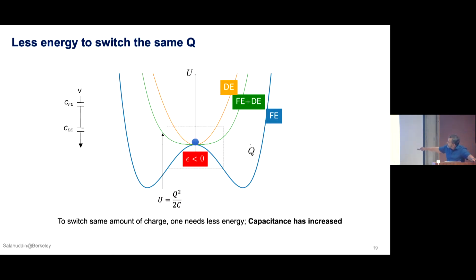But think about this W energy landscape, and let's say that I put a parabola with it. If these two are added properly, then we will get this green parabola. The y-axis is U, the x-axis is Q, so you can see that to switch the same amount of Q for the green, I need a smaller energy than the orange. That means I'm switching the same amount of charge at a smaller energy, which means that capacitance must have gone up. So I'm putting two capacitors in series. Our standard textbook will say capacitance should always go down.